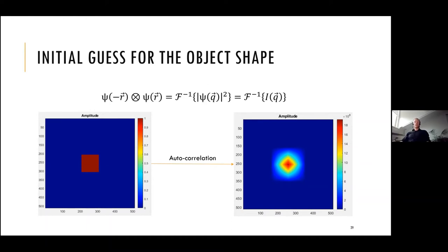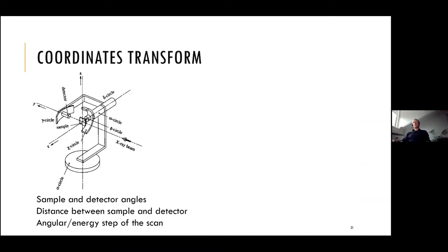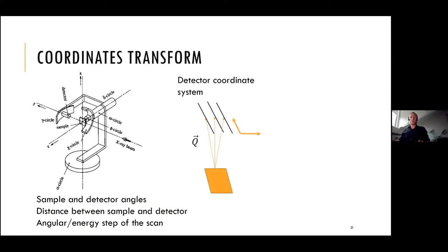After the phase retrieval is done, the next problem is basically a coordinate transformation, because you measure the data in the coordinate system of your detector, which is not orthogonal. And to go back to orthogonal space where you can align your object with the reciprocal lattice vectors of the crystal, you need to do this transformation back to the so-called laboratory frame. For that, you need to know the sample and detector angles. You need to know the exact distance between the sample and detector, and you need to know the angular or energy step of the scan. So this is how it looked in the detector coordinate system.